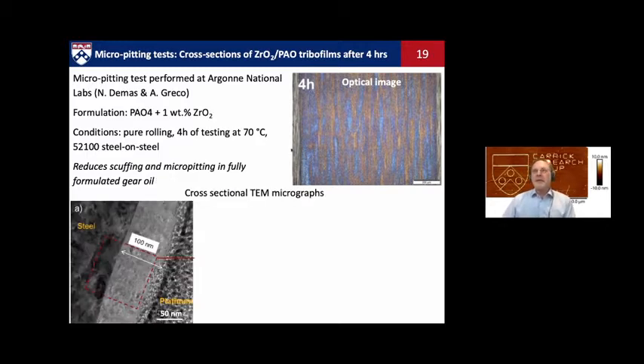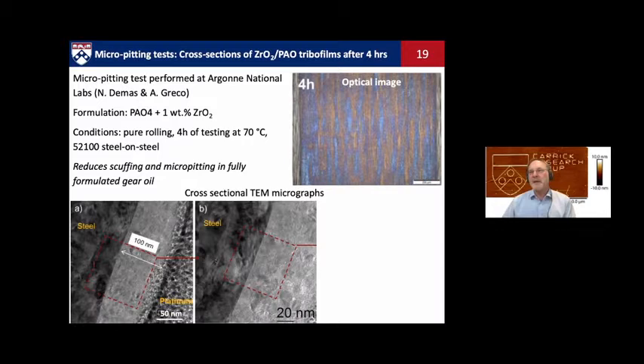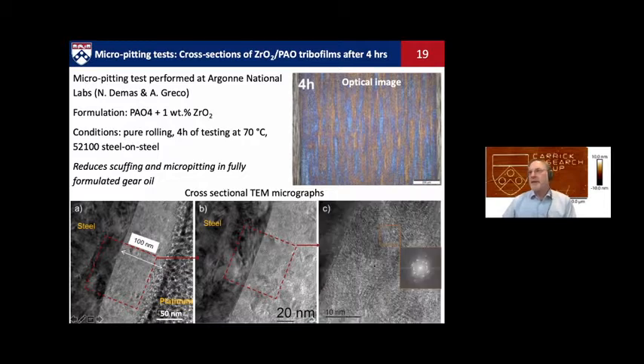So just to show you what these look like, here's one of Argonne's tribofilms. Here's a cross-section using focused ion beam. Here's the steel, and sort of similar in character to the ZDDP, we see this solid, dense film built up on the surface. There's a nice sharp interface with the steel, and we see a very dense uniform solid. The zirconia has somehow compacted into a uniform film. It is not a porous, loose association of zirconia nanoparticles forming debris. This is actually a good solid film with very few observable pores.